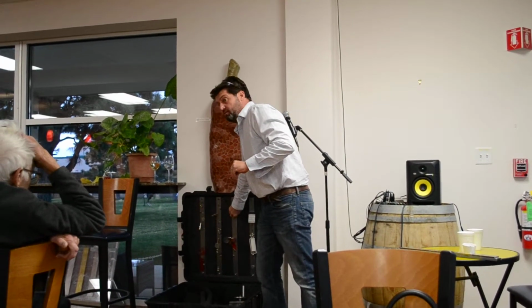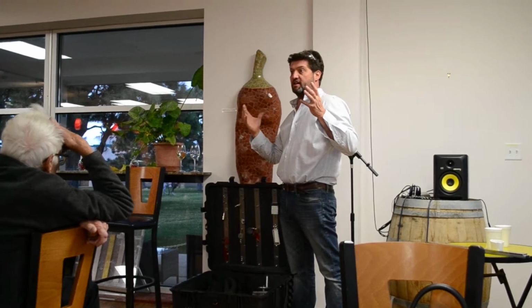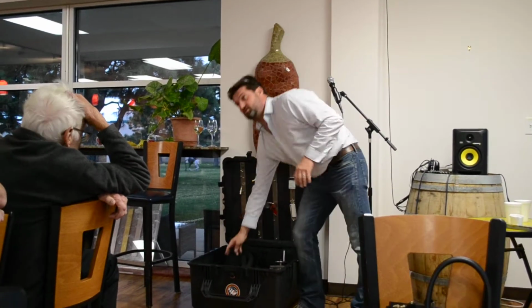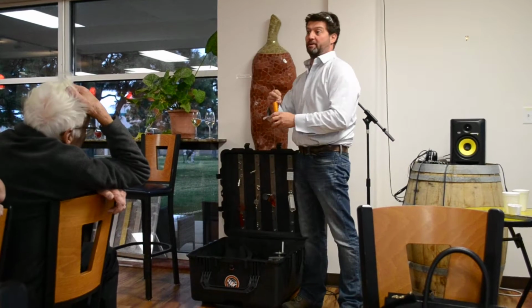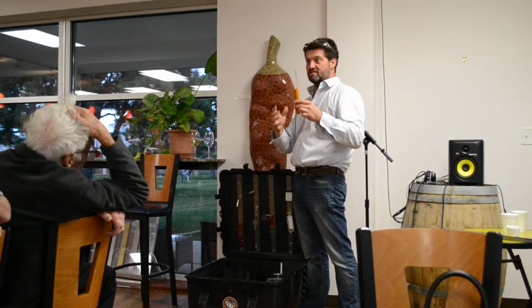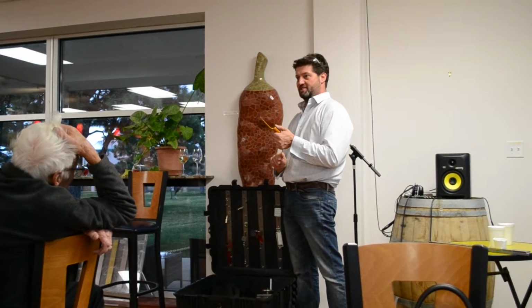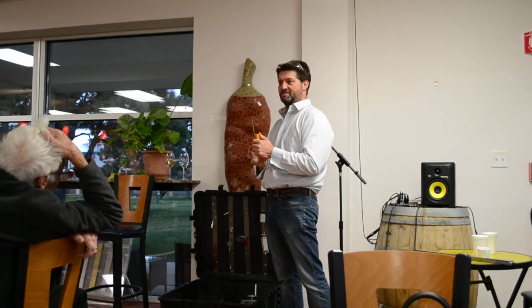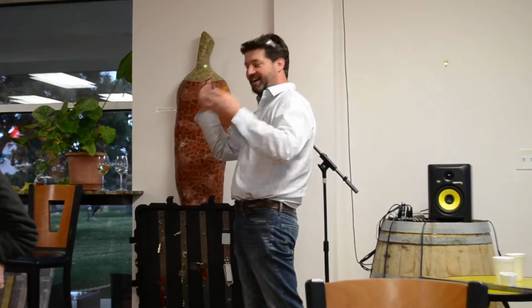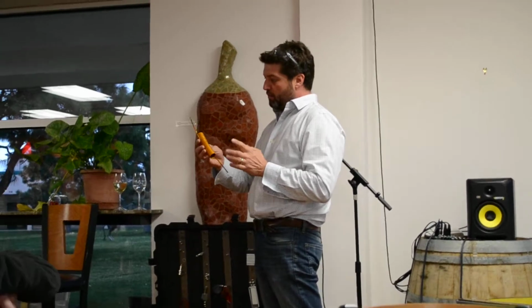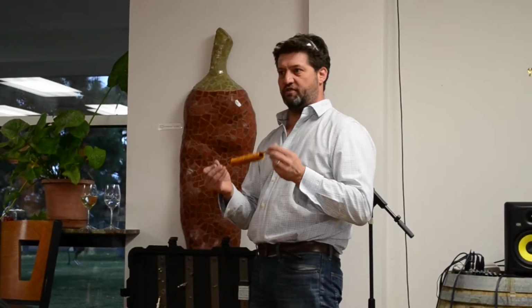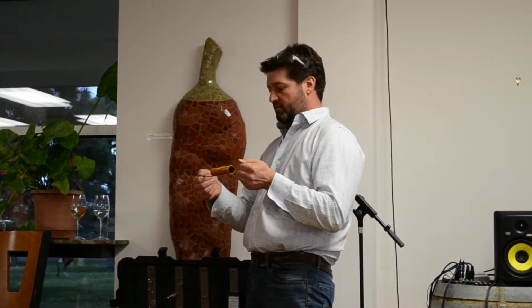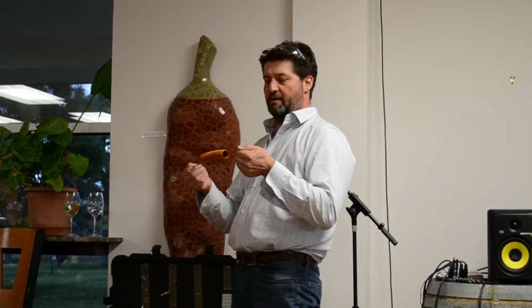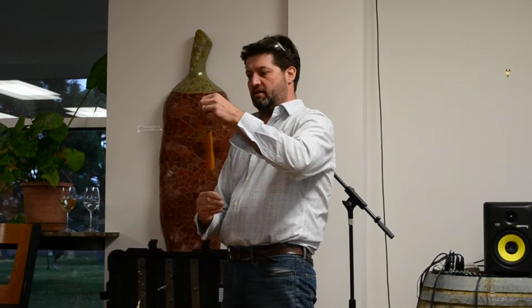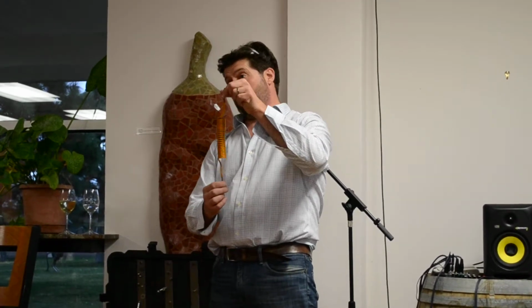Okay, so we can get to about 45 Tesla just by being able to keep our conventional conductor cold enough by pumping huge amounts of water through this. This facility uses something like 10% of the power demands of the city of Tallahassee, where it is, when it's up and running. What we do here in Los Alamos is we're the pulse field facility. So we get away from this heating problem by turning our magnets on for a very short period of time. So I take my coil of wire and first of all I get it cold.